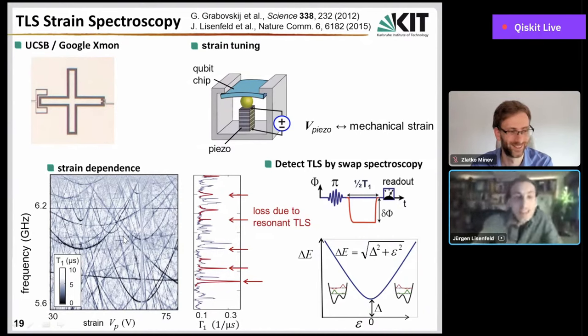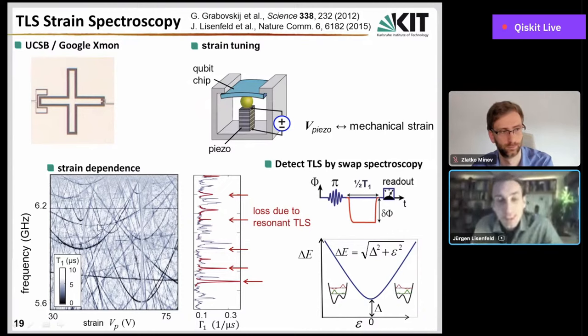If you look closer here, you actually see one line which is not depending on the mechanical strain. It turns out that this was also not a defect, this was just a parasitic resonance, or the resonance from a second qubit on the same chip. We could move this by applying some flux. And this nicely shows that such a strain tuning measurement allows you to distinguish defect resonances from parasitic circuit resonances, which can also be very helpful to debug your microwave engineering.